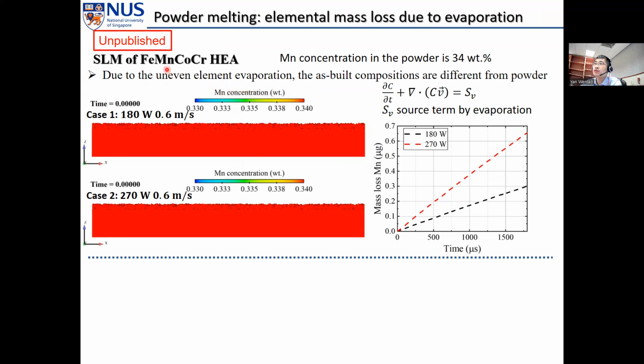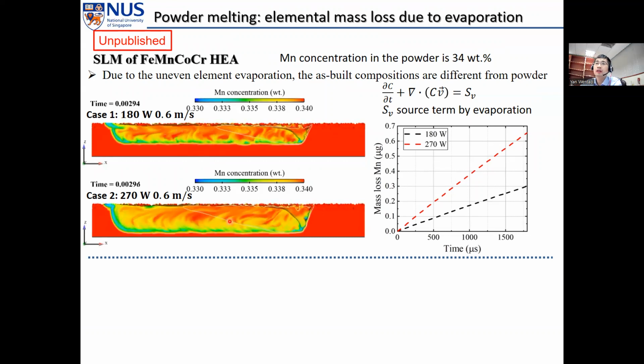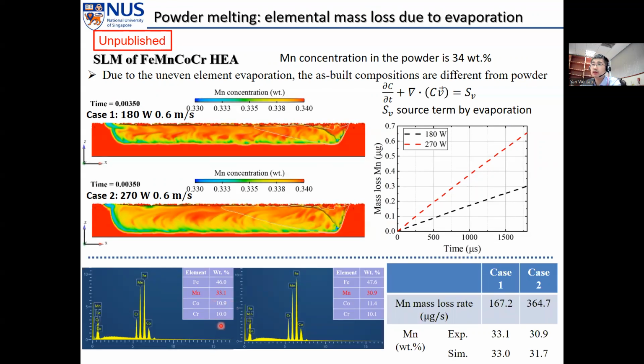This is a very complex high entropy alloy, and the manganese concentration in the powder is around 34 weight%. But with different laser melting parameters, we can see this concentration is varying with locations and also the manufacturing parameters, because manganese has a different evaporation rate from other chemical elements. And these are experimental results. You can see the as-built part with different manufacturing parameters, the manganese concentrations are different. And our simulation agrees pretty well with the experimental results.